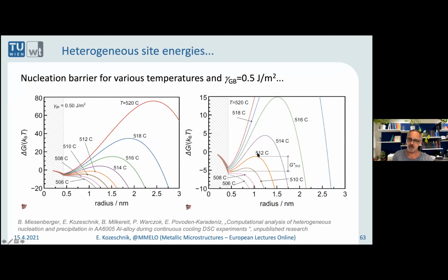This is a close-up for 512 Celsius, where you can see that the nucleation energy goes down immediately. But please ignore this shaded area because that's outside of the validity of one of the models. So start at nucleation radius of 0.4 nanometers, which is probably 4, 5, 6 atoms large. For that, you can see that nucleation barrier goes down, and then you have a little hump. Still, you're negative in value, but the nucleation barrier must still be overcome.